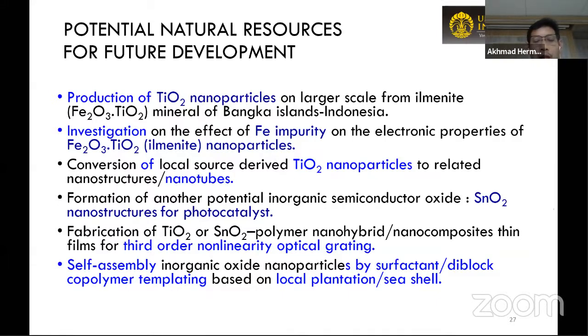And there is another nanostructure material that can be developed further, for example, for photocatalysis to degrade pollutants from the liquid environment. Remember that the tin metal that has been extracted from the Bangka and Belitung mining, the SnO2, is also very potential, especially in the form of nanostructure. So if we can make it as nanoparticles, nanotubes, or some other nanostructure, of course, its use for photocatalysis and also maybe dye-sensitized solar cells can be enhanced.